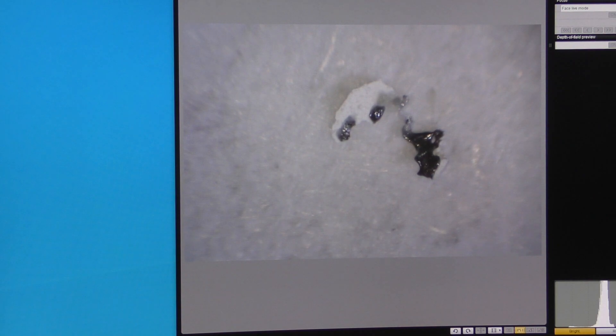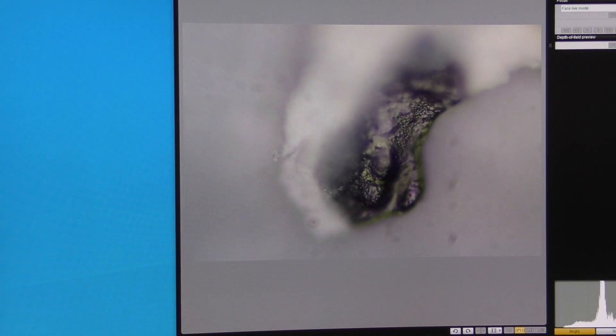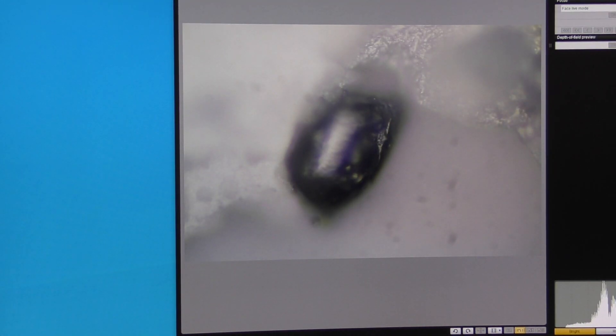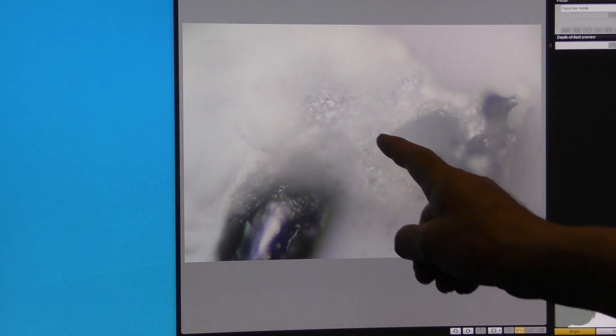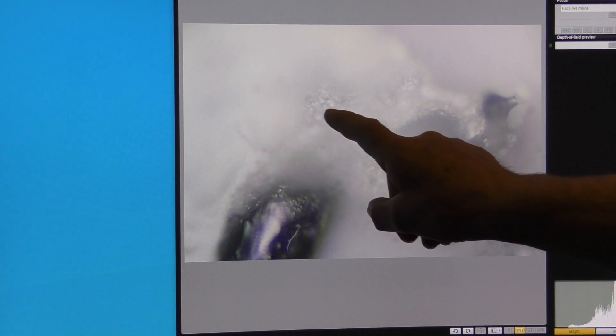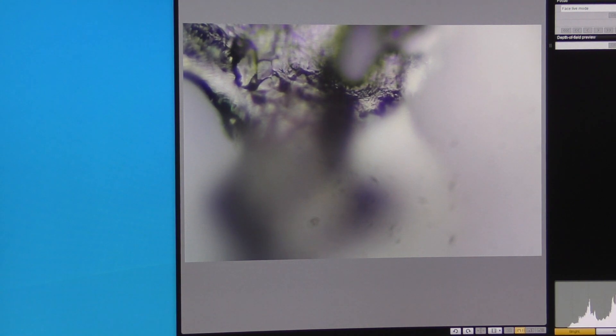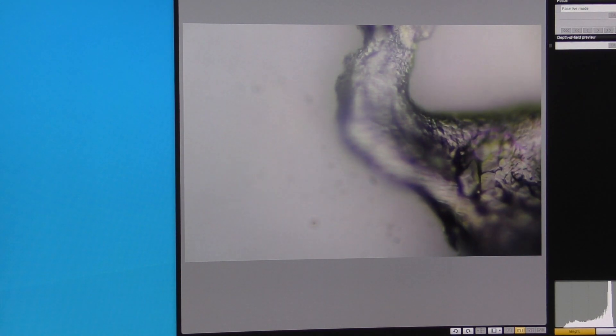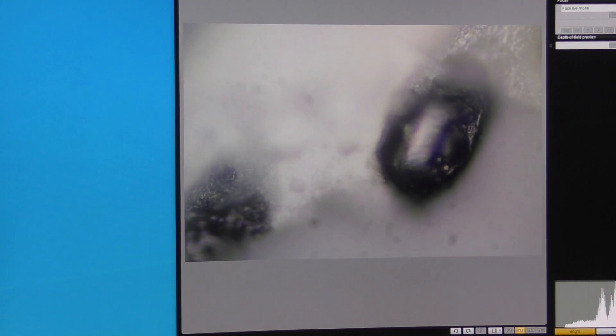Now, let's just go and have a look at those at 400 times magnification. And there it is. Look! So that's solid titanium dioxide attached to the white powdery stuff. Wow! Look at that. That's a lovely... You can see that that's a molten shape because look, it's like a blob of solder. And we can see here, look, like an intercrystalline state where it starts to change from very small microcrystals. As I said, the crystal structure changes as the cooling rate changes. Look at these large crystals here. Fascinating, isn't it? So this piece has come off all in one piece because it's no longer a powder. It's actually a partial melt. I have to say, it's fairly satisfying when theory turns into reality.